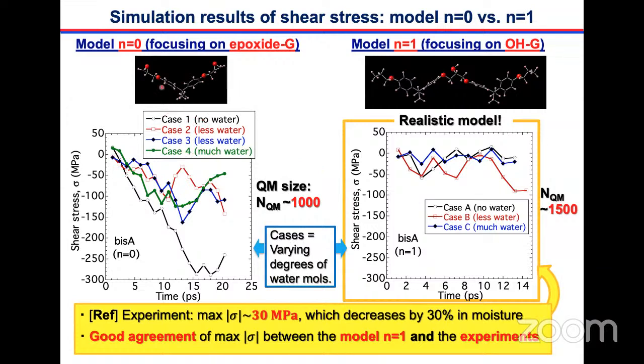In the n equals 0 case, case 1, the maximum shear stress is about 300. This value is about 10 times larger than the experimental value. The experimental value of the maximum stress is 30 megapascal, which decreases by 30% in the presence of moisture. In the computer simulation, the existence of moisture lowers the maximum shear stress by about half. That means it is still 100 to 150 even after the insertion of water molecules. This is unrealistic because it is too large compared with experiment.